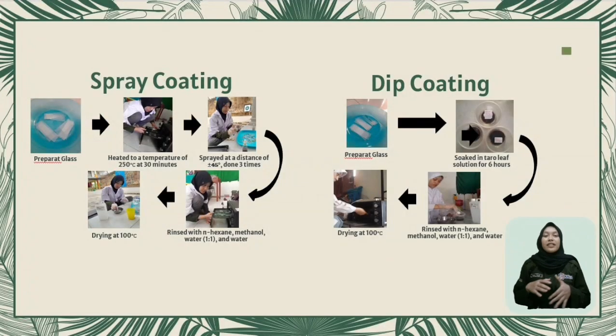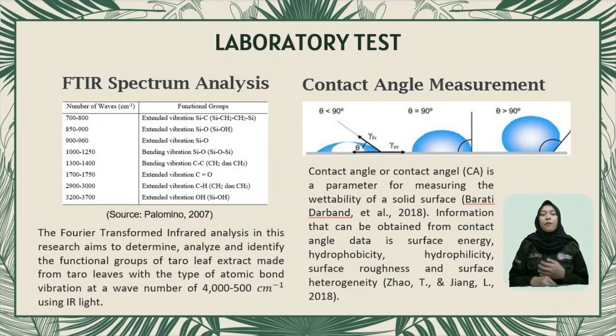We carry out the dip coating process and spray coating process. The spray coating process include prepared glass heated to 250 degrees Celsius at 30 minutes, and then spray distance more or less 45 degrees, and then rinse and dry. Meanwhile, for the dip coating process include prepared glass soaked in taro leaf for 6 hours, and then rinse and dry.